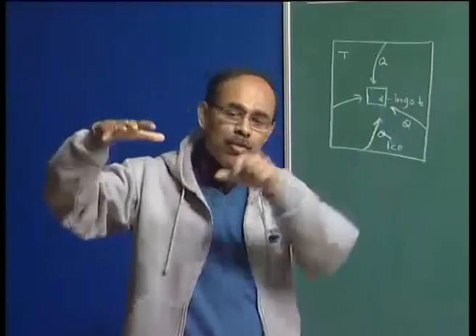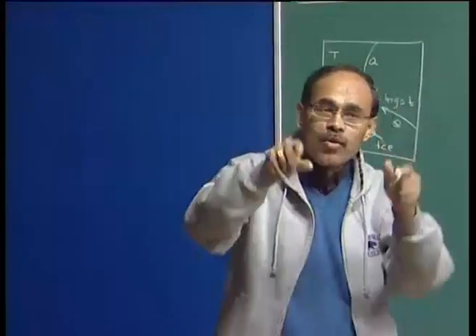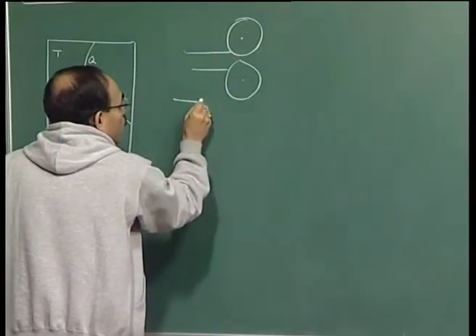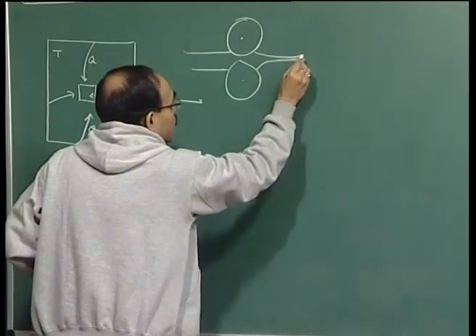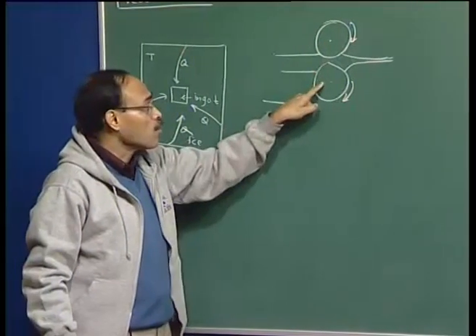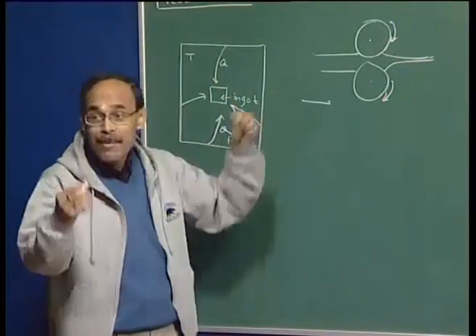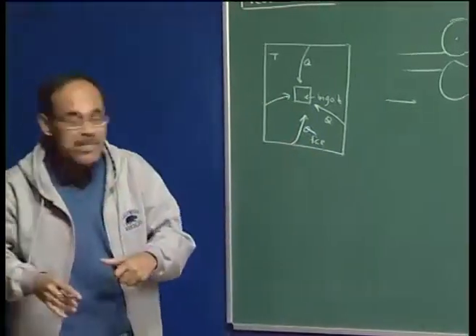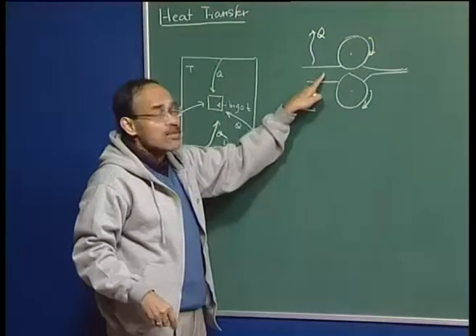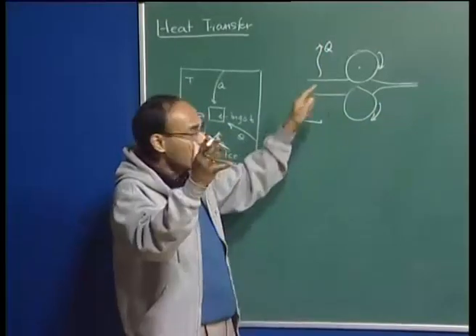When a slab is moving between rolls, there is going to be contact resistance and heat flow; the rolls are water-cooled and take away heat from the slab. Heat is evolved within the solid due to mechanical working — conversion of mechanical energy to heat energy — with an associated efficiency factor. So we have heat transfer from the surface, heat being lost by various mechanisms, and heat evolution within the solid because of mechanical working.